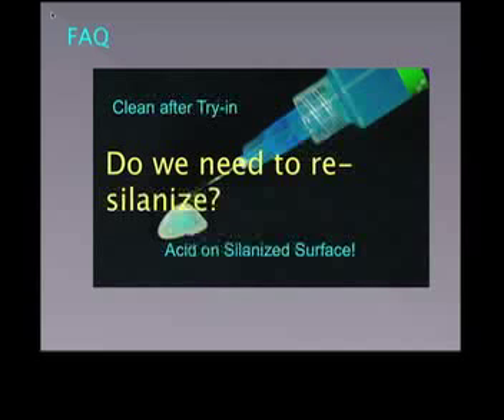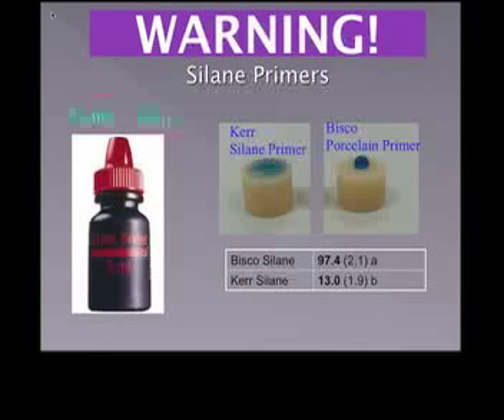So what we want to be careful of, because the minimal contact angle of what used to be really the only dog in the show, this Kerr silane primer, indicates stable covalent bonds were not formed. If you look at the left side, you'll see that the contact angle is almost like having nothing on that substrate. But when you look at BISCO's porcelain primer, you see that contact angle nice and tight.